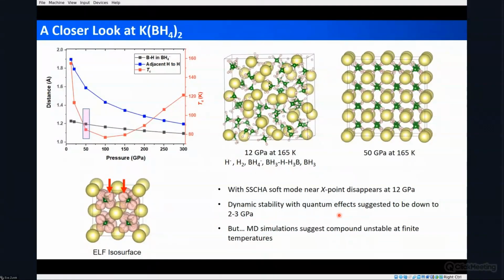What I do note, on the other hand, though, is that though these TCs are very high at low pressures, if you take a look at the molecular dynamics simulation, what we find is that at these lowest pressures, so 12 GPa or whatnot, the dynamics predicts these structures to be actually unstable. So you're going to overcome barriers, and the system will form these kind of unwanted units and actually an insulator, and it's not going to be good for superconductivity. So our molecular dynamics simulations suggest that you need at least 50 GPa of pressure to stabilize these systems, and therefore looking just at the dynamic stability is not sufficient to predict when different structures with various TCs, high TCs, might be stable.